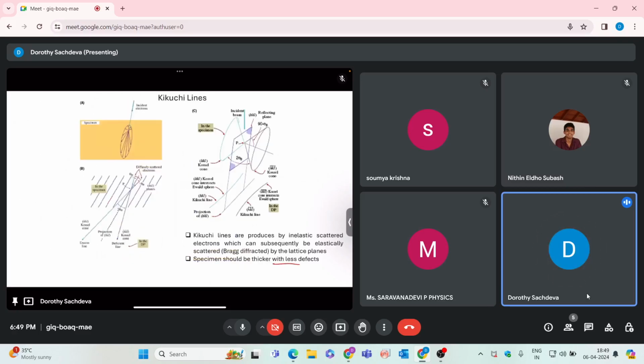This we have discussed in the previous classes about the Kikuchi lines. Kikuchi lines are formed by the inelastic scattering of electrons, which then subsequently are elastically scattered. Elastically scattered means what? Bragg diffracted by these lattice planes. So to observe the Kikuchi lines on your screen, the specimen should be thicker with fewer defects. If the specimen is very thin, then you won't be able to see the Kikuchi lines. You will only be able to directly see your diffracted spot. For a thin specimen, you can directly see diffracted spots.